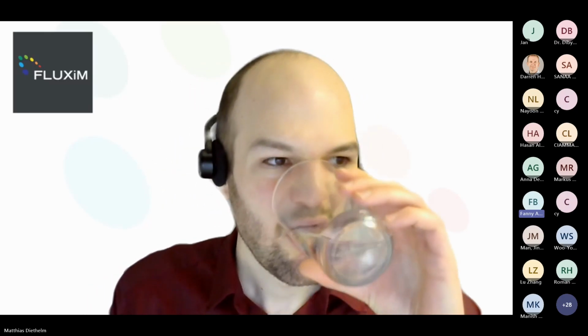Yeah. A question which popped up is, you also worked on a publication specifically with respect to strain. Since I myself didn't come in contact yet with this keyword in degradation, can you highlight what the factor strain is in degradation? In this case, what we've seen also in previous studies is that when you have expansive strain, that's really detrimental to your stability because the interatomic distances in your lattice become larger. That makes it easier for things to move around. So if we already have a rather soft lattice where we have ion migration or a formation of defects, that can be enhanced when we get an expansion of the lattice. And we've seen that if you're able to produce a compression in the perovskite lattice, that can enhance the stability.